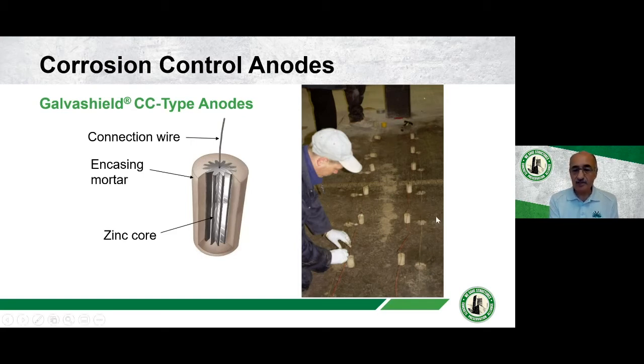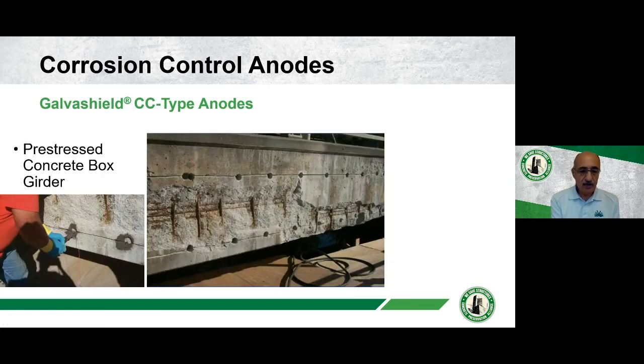This is normally a grid formation, so you get a lot better current distribution than if you've got a single line of anodes as you might have in a patch repair. And this is called corrosion control. We call it corrosion control because you're trying to extend the surface life of your structure. So you are reducing the rate of corrosion significantly. You may not be stopping it totally, but you're extending the surface life by 20 years or whatever your design might be. Another example is a pre-stressed concrete box girder.